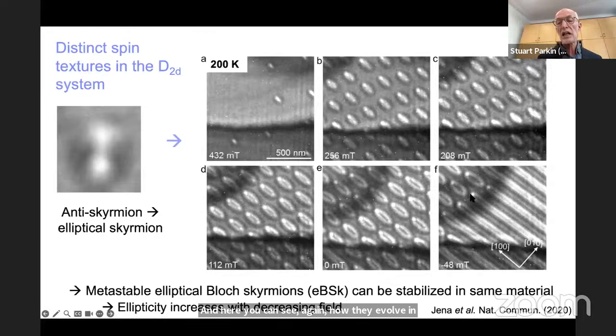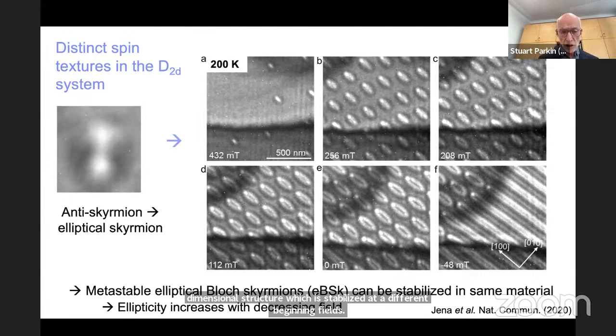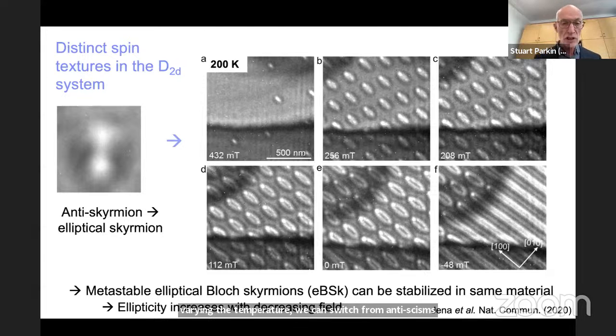And in the bottom right, you can see how these elliptical Bloch skyrmions evolve from the helical one-dimensional structure, which is stabilized at different magnetic fields. And the reason for forming these structures is these elliptical objects, which, by the way, have the long axis of the ellipse only formed along one of two perpendicular crystallographic directions. And along those directions, as I mentioned at the very beginning, they're the directions that favor a Bloch type wall, and the Bloch type walls themselves have a lower magnetostatic energy than the Néel walls. This is why they're formed. And so we found these objects, and it turns out by varying the temperature, we can switch from antiskyrmions to these Bloch skyrmions, or at the same temperature, we can see both.